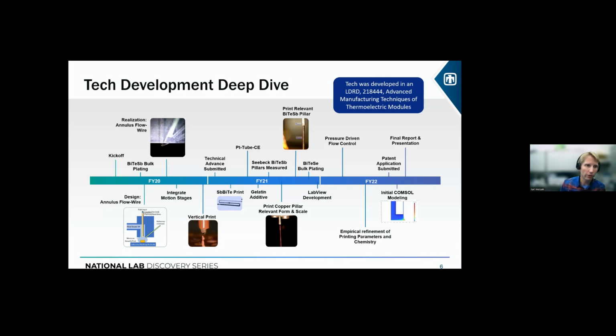The LDRD program starts off with a proposal process, and luckily a proposal was awarded for the development of thermoelectric materials. That kicked off in FY20. We started off with paper scratch of what this technology could be, and from that, within a couple months we had a functional demonstration of this technology. Now, very rough. Some of the first features we printed were fairly dendritic, rough surfaces, not super smooth. But we were able to continue to develop and learn about this technology to refine the process to eventually print columns of materials, so copper columns and thermoelectric columns.